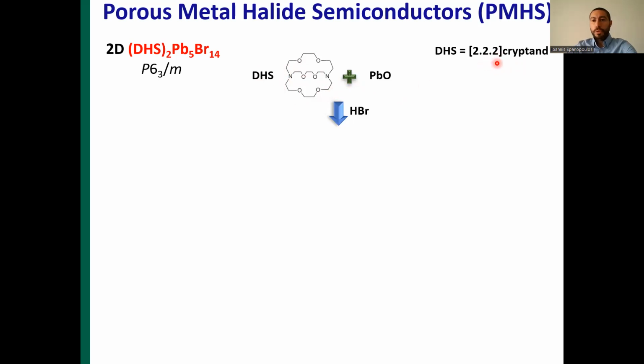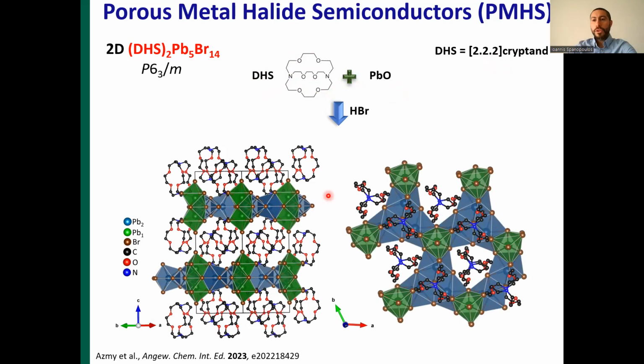Reaction of the 222 cryptand linker, in that specific case we call it DHS, with lead in acidic media, gave rise to the first 2D porous metal halide semiconductor. This is part of the structure, looking down the 110 direction, in plane. The structure consists of 2D inorganic layers of lead bromide clusters that are separated and charge balanced by the cryptand linkers. On the right, there is the representation of one inorganic layer and one organic layer.